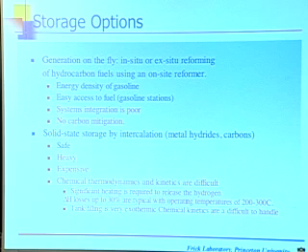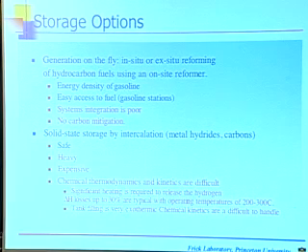That is, the safety issue is based on the fact that when the hydrogen is in the metal hydride, it's sitting in a nice, deep thermodynamic well. That is, delta G is very positive for getting it out. But of course, you want to get it out when you run your car. So you have to heat up your system quite a bit to get the hydrogen out. So there's a big waste of energy in getting the hydrogen out. On the other hand, you need to put hydrogen in when you're refueling your car, and that's going to have a major exotherm associated with it. And so you have to be able to take care of that. Again, you can't fill it up too quickly or you'll generate too much heat and you'll have issues. So the in and out here is somewhat of an issue.